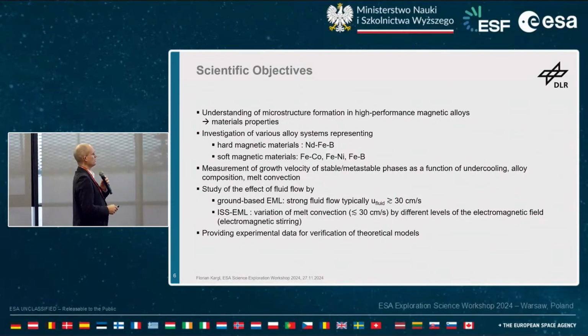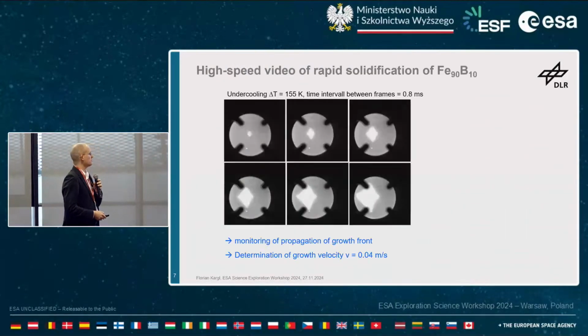What we look into is measurement of growth velocities of stable and metastable phases as a function of undercooling, alloy composition, and melt convection. And the melt convection topic that I explained briefly before: ground-based strong fluid flow, ISS EML facility, variation of the fluid flow conditions, and we can have a look at the impact of that. And it's clearly here providing experimental data for verification of theoretical models that describe, for instance, the growth process.